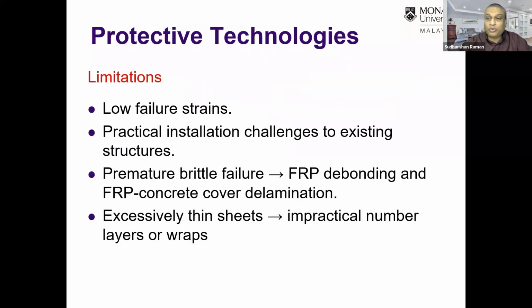But these composite laminates do come with their own sets of limitations, especially when they are subjected to blast or impulsive loadings. Some of their limitations are listed here. They have low failure strains, and when you want a structure to be strengthened against blast and impact loading, you would expect it to have high failure strain rates. There are practical installation challenges for existing structures, and they can sometimes fail prematurely in a brittle manner due to debonding or FRP and concrete cover delamination. Usually these FRP composites come as FRP wraps in excessively thin layers, so you need an impractical number of layers or wraps to strengthen a structure effectively against such impulsive loadings.